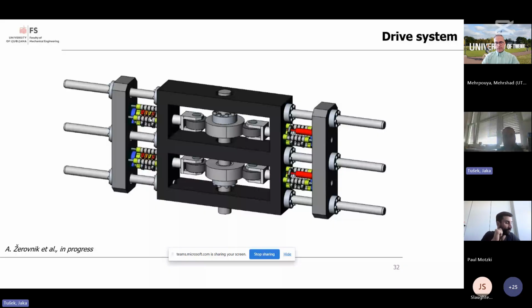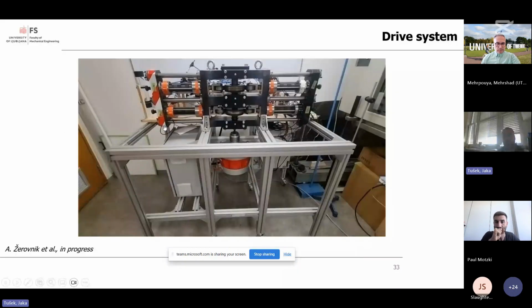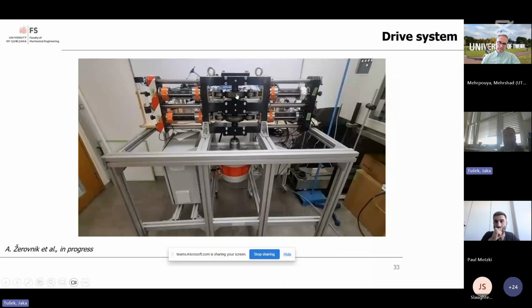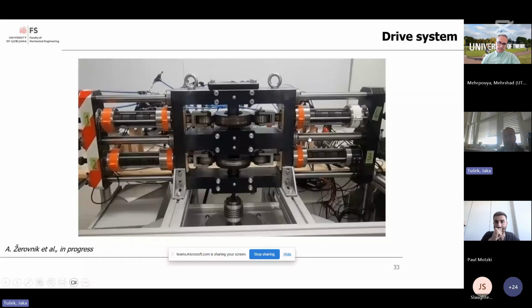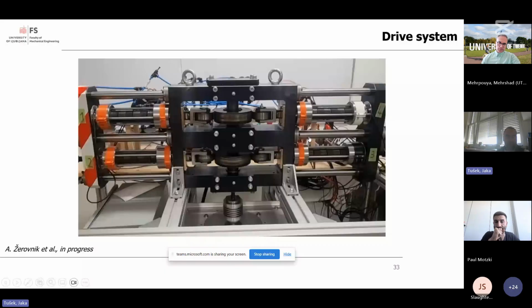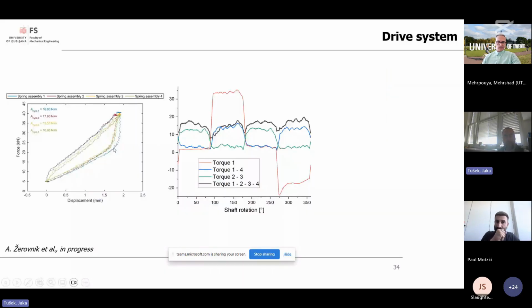So far, the device has only been tested mechanically. We're using springs here that simulate the elastocaloric regenerators, and this allows us to characterize this system from a mechanical point of view. This plot shows this characterization. This is the mechanical response of four springs, and this plot shows torque over one cycle. As can be clearly seen, if only one regenerator, or only one spring in this case, is used, the torque fluctuates quite drastically, which is very bad from the electromotor point of view. If we use two springs at the same time, the torque fluctuates less, but there are still some significant fluctuations. If we use four regenerators, as shown here with the black line, the torque is more or less constant at around 15 Newton meters.